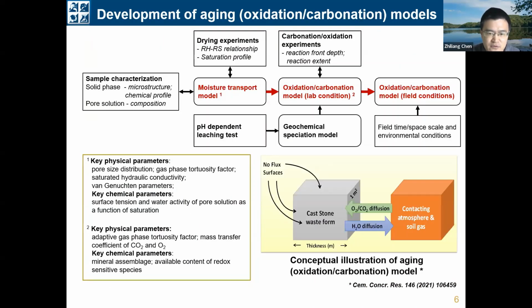And specifically for the aging model, we firstly developed a drying model to describe the moisture transport between the Cast Stone and the environment. And then we further incorporated the diffusion of oxygen and CO2 into the drying model to develop an aging model. And finally, by extrapolating the aging model with the input of the aging conditions in the field scenario, the aging model can be used to estimate the long-term oxidation and carbonation depths.